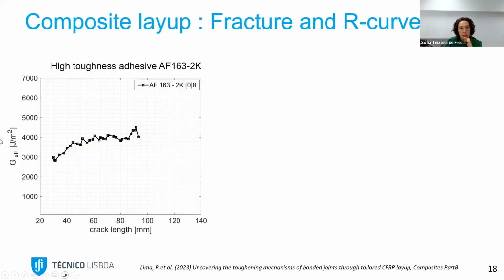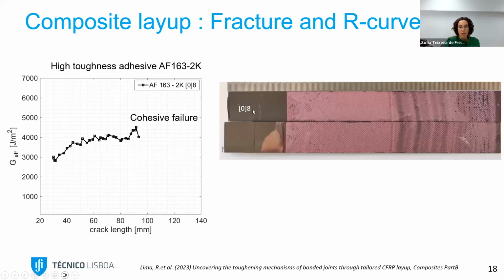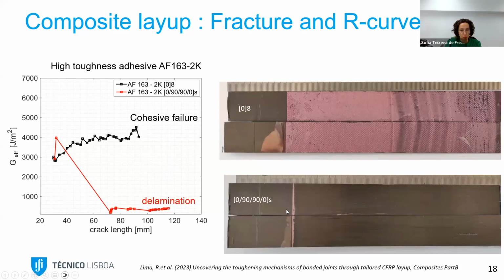So these are the first results. What you see here is again this graph that I was showing in the beginning of the presentation. So here is the energy release rate against the crack length. So this is the reference specimen. So all 0 degrees ply. And what we see is that the crack propagates always inside the adhesive. So you have a complete pink fracture surface. So there is no sign of fracture in the composite. When we have the cross ply, the 0, 90, 90, we see a very different fracture surface. So we see a little bit of adhesive here, but then the crack deflects to the composite, and it delaminates once it reaches the 0 degrees.